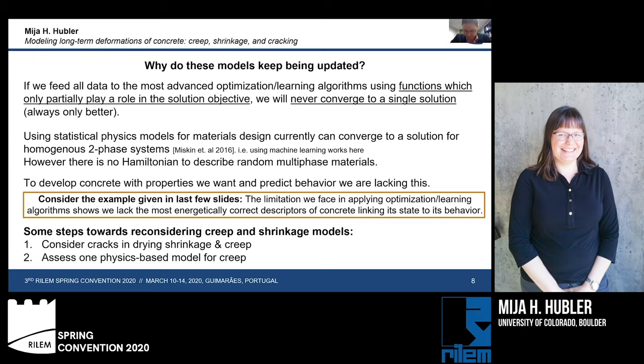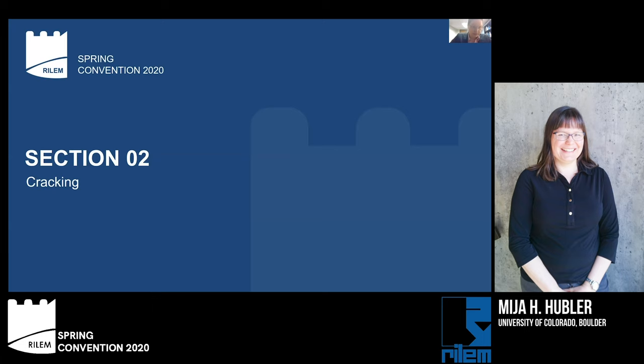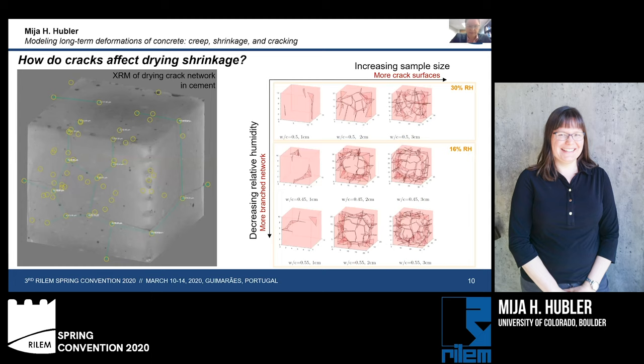Okay, so first, here in section two, let's take a closer look at cracking. How do cracks affect drying shrinkage? Well, we can do an X-ray of a drying piece of cement, and what we observe is a crack network in the cement. The interesting thing that we find if we do a series of these is that with increasing sample size, going here from 1 centimeter to 2 centimeters to 3 centimeters, we have more crack surfaces.